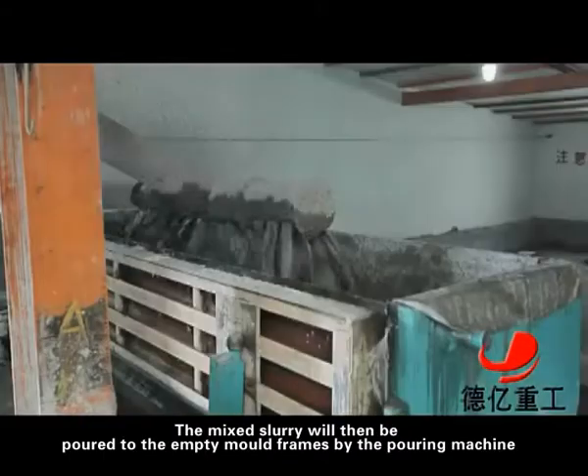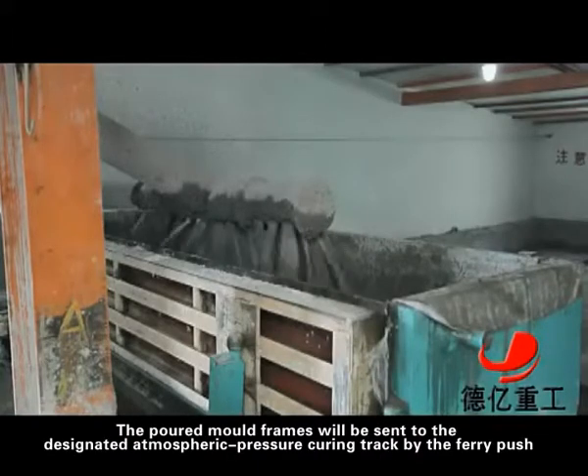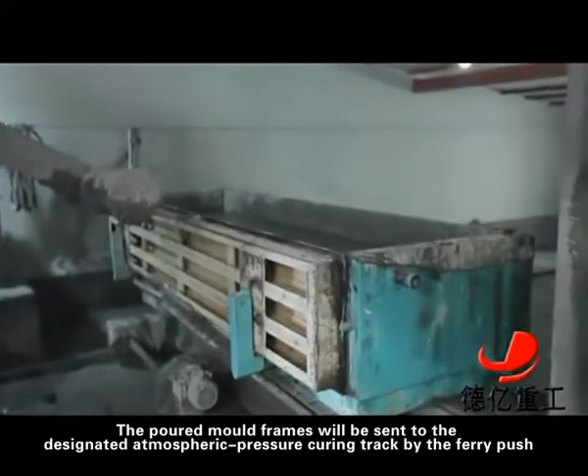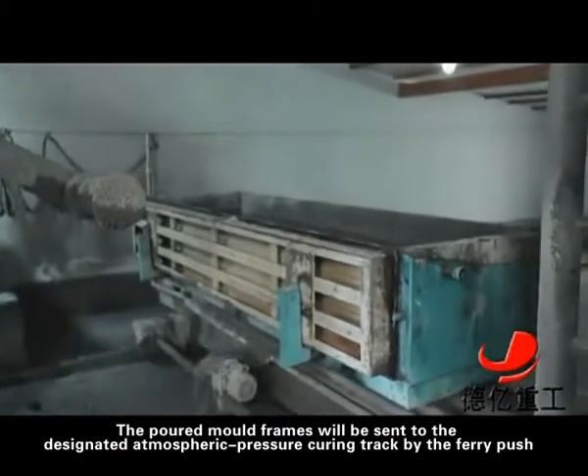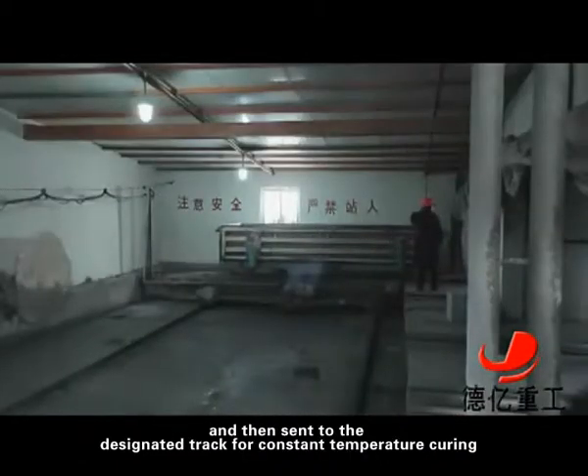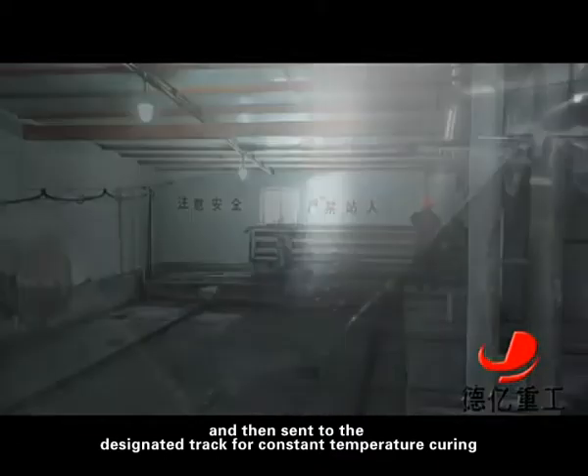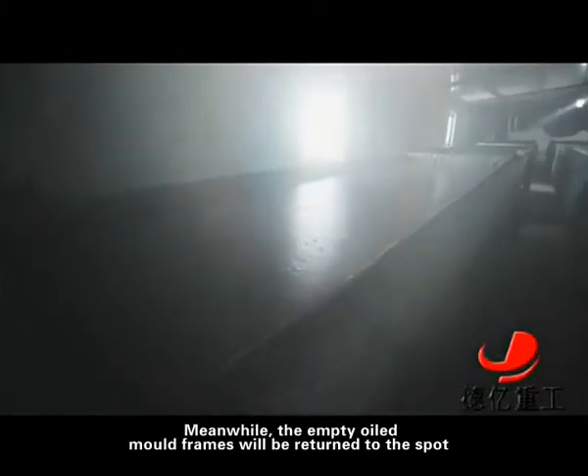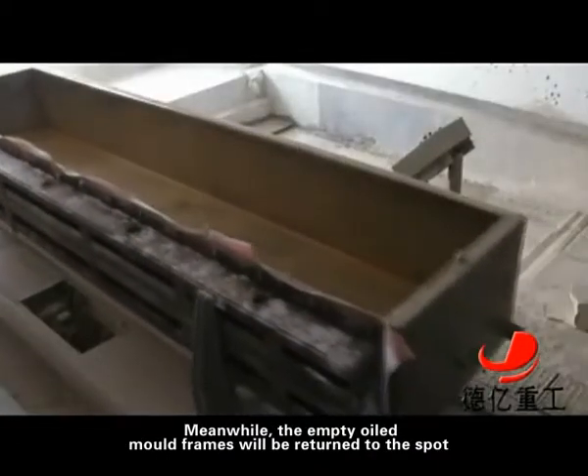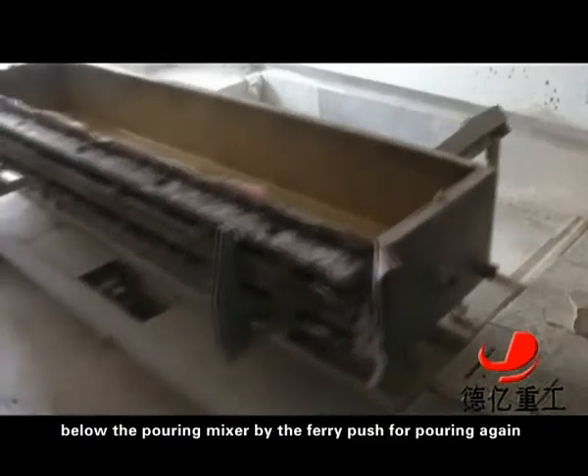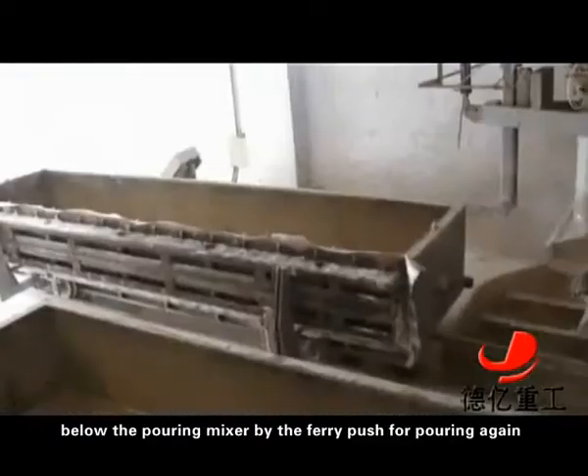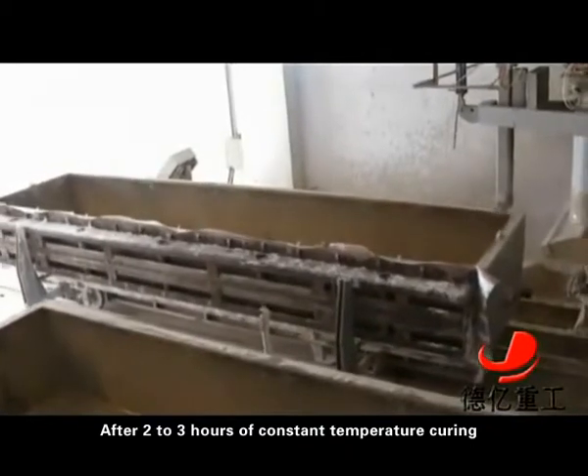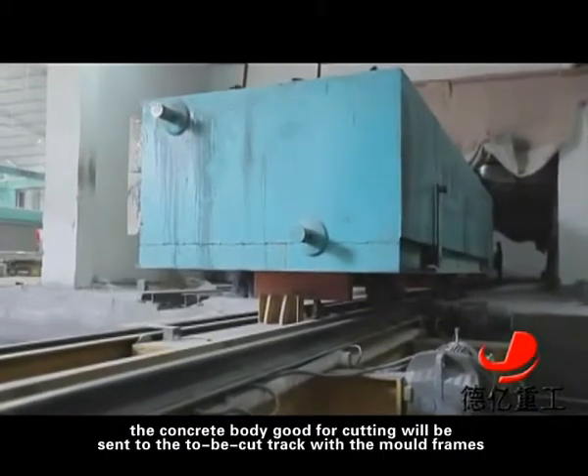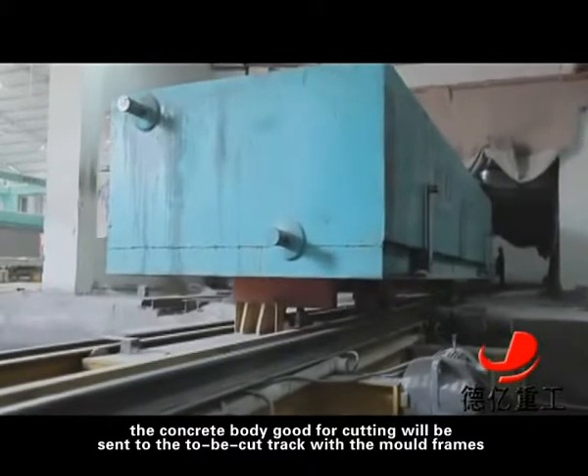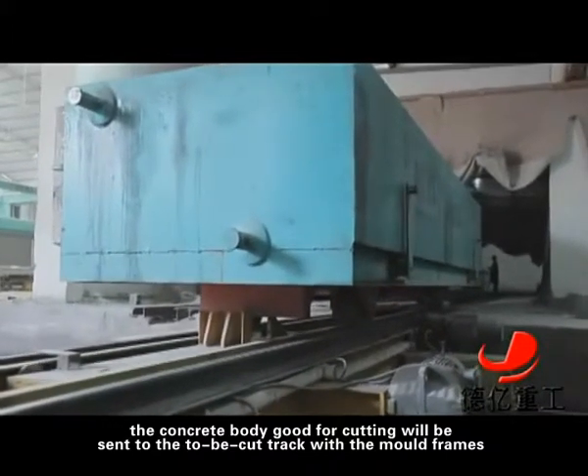The mixed slurry will then be poured into the empty mold frames by the pouring machine. The poured mold frames will be sent to the designated atmospheric pressure curing track by the ferry push, and then sent to the designated track for constant temperature curing. Meanwhile, the empty oiled mold frames will be returned to the spot below the pouring mixer by the ferry push for pouring again. After 2 to 3 hours of constant temperature curing, the concrete body good for cutting will be sent to the to-be-cut track with the mold frames.